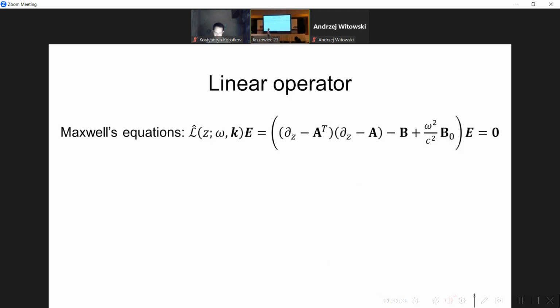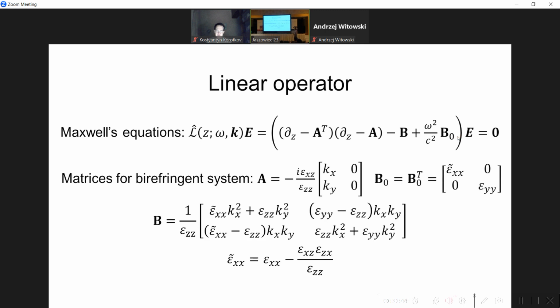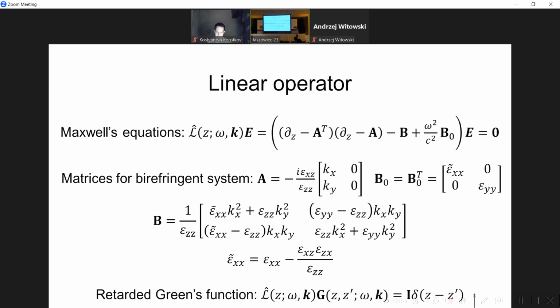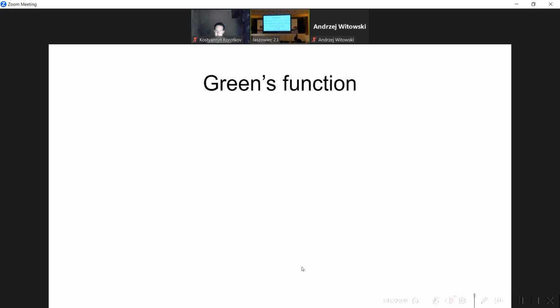We start from the Maxwell equation for a birefringent system, and using standard techniques, we can reduce this problem to a second-order differential equation for a two-dimensional vector of electric field with matrices A, B, and B0, which depend on the component of the dielectric tensor. In our case, the tensor is a symmetric matrix, and the solution for the electric field can be given by the retarded Green function, which is a solution of this equation.